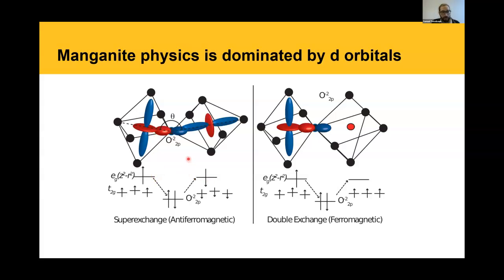But even more importantly, this hopping interaction is controlled by the angle between the 2 perovskite octahedra. What that means is that by controlling this octahedral rotation angle, you control the intersite coupling. And so this can tune between a ferromagnetic state, which likes a lot of intersite coupling so that you can get good conductivity. Essentially, it favors hopping interactions. On the other hand,